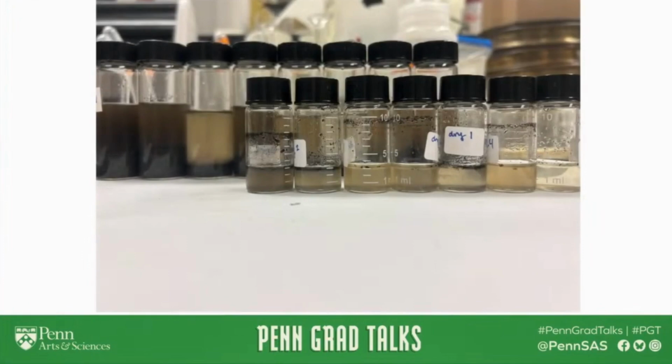By using density solutions of varying densities, we can actually separate the weights of our tire particles and assign them by extracting what's floating and what's sinking to specific density ranges. Now, what we found was striking from this.